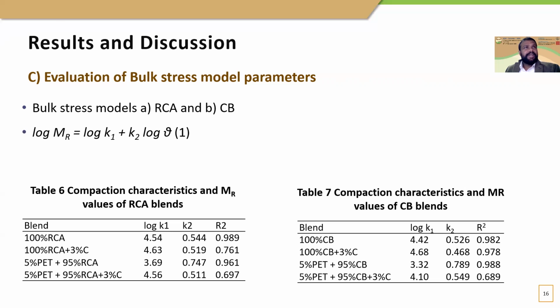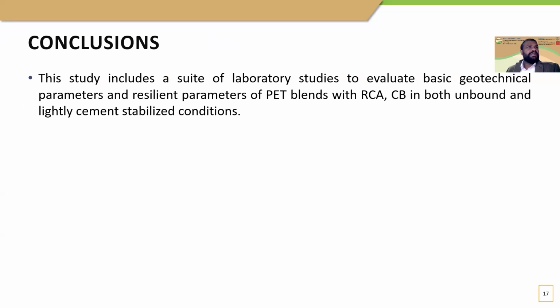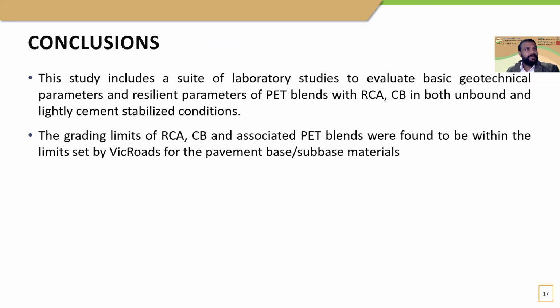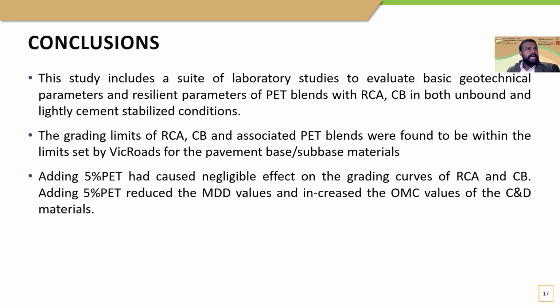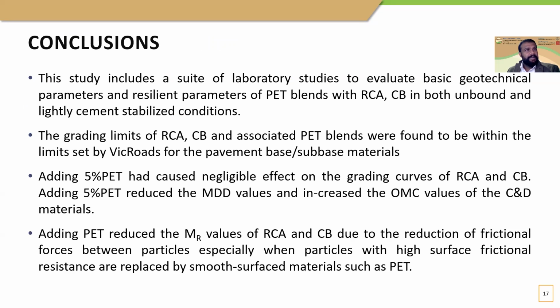And moving on, the next slide is the conclusion. The study includes a suite of laboratory studies to evaluate basic geotechnical parameters and resilient parameters of the PET blends with RCA and CB in both unbound and cement stabilized conditions. The gradation limits of RCA and CB and associated PET blends were found to be within the limits set by VicRoads for pavement base and sub-base materials. Adding 5% PET has a close to negligible effect on grading curves of RCA and CB. Adding 5% PET reduced the MDD values and increased the OMC values of the C&D materials.